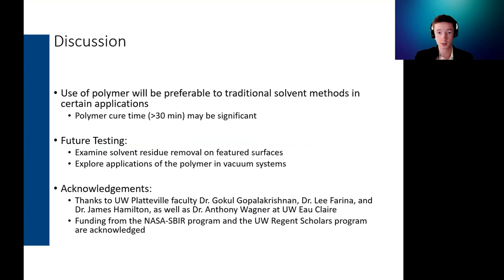So in the applications we tested, First Contact outperformed solvent methods in a number of situations. For particle contamination, First Contact removed titanium dioxide contaminants more effectively than solvents in almost all cases. For removing organic residue from solvents, First Contact was comparable to solvents but it did leave a lower residue which was nice. For liftoff it gave a different result than solvents would, but that result is more preferable as it reduces the amount of post processing you'd have to do.